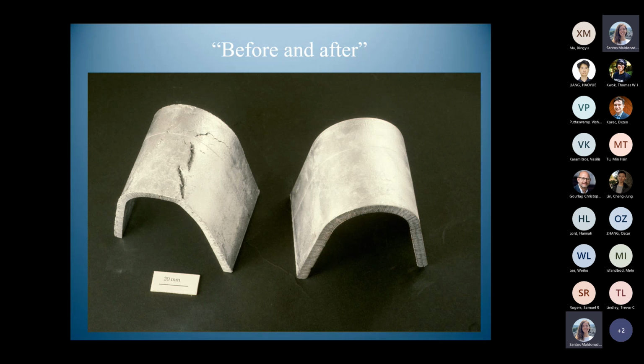These are two of the castings. This one has got, well, when you bend something, you expect a crack to go along the axis of the bend. Well, there's not one crack on the axis. There are these cracks just slightly off the axis, one going down here, another one going across here, another one down the back you can't see. And that gives you the clue as to how they formed.